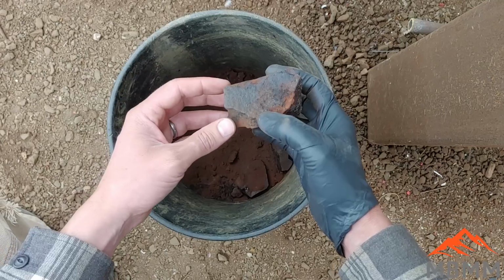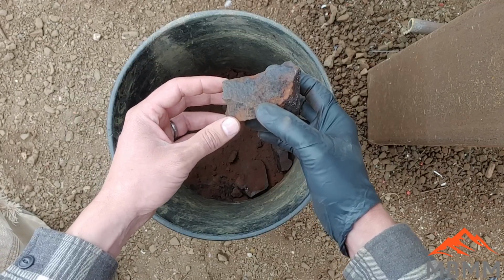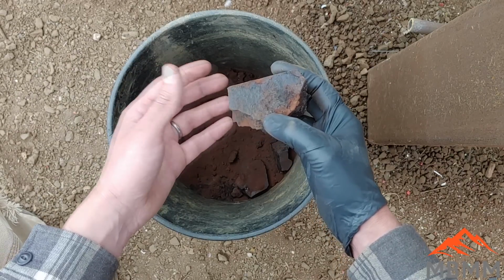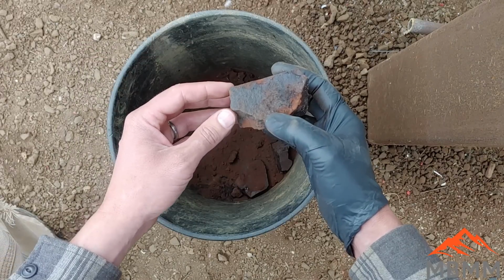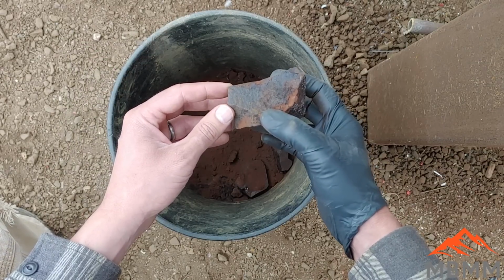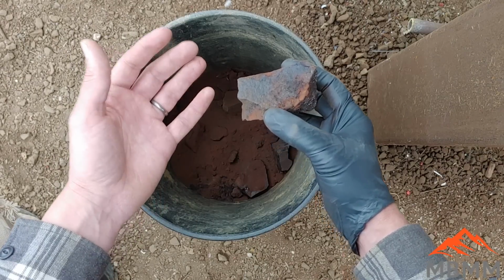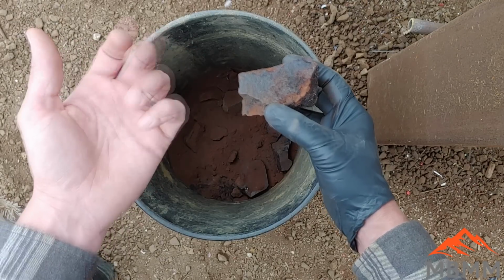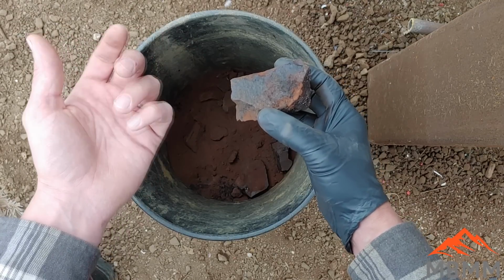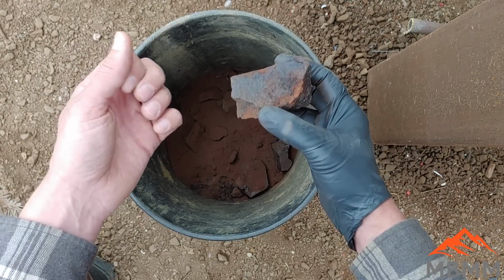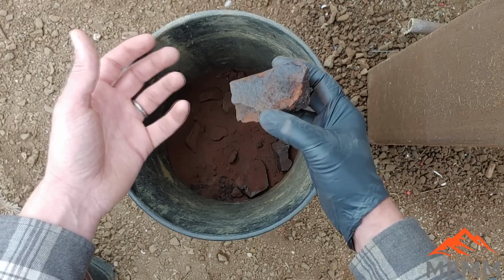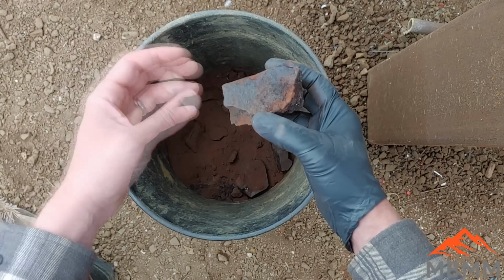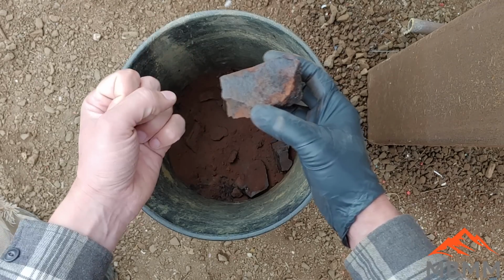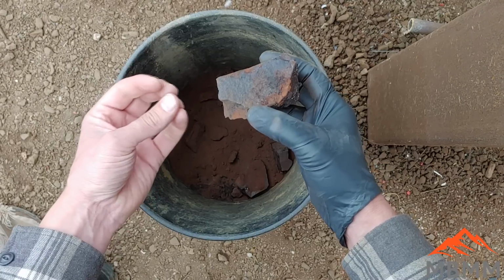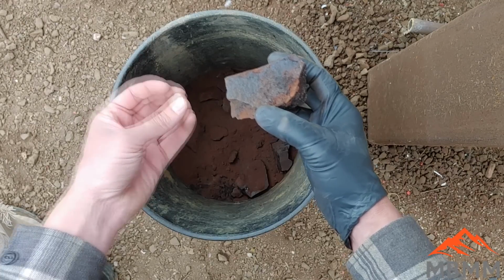And so essentially you flood the system with metallic iron, which reduces all the metals that are less reactive than itself. And you guys can check out the metal reactivity series, I think it's called. Google it, and you can see all of the metals and how reactive they are compared to each other. But by adding the metallic iron, you pull all the sulfur off those less reactive base metals. You create a huge amount of FeS, just iron sulfide, and all the base metals get reduced to metallic form, and they go down and they collect in your collector metal at the bottom of your smelt and then in your cone mold.